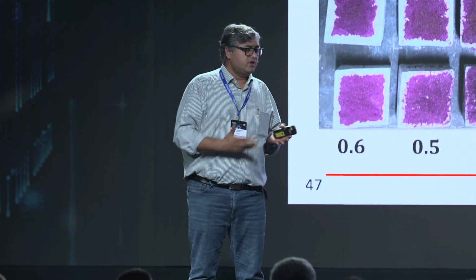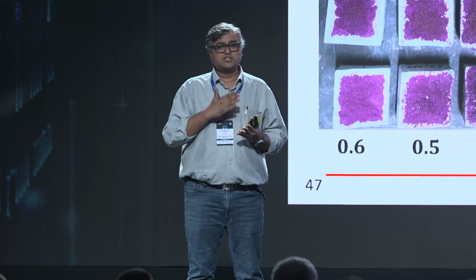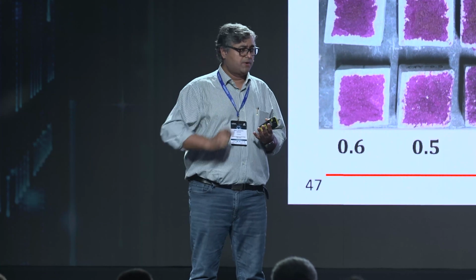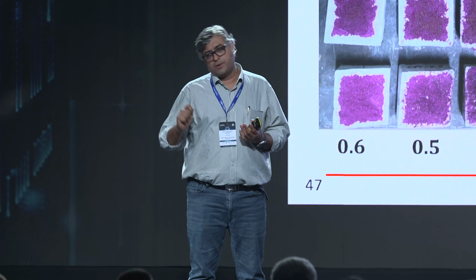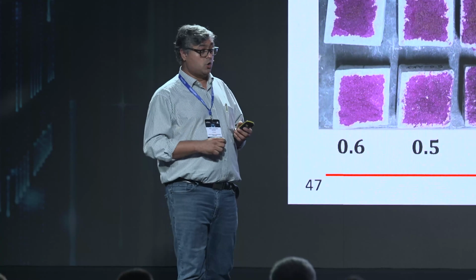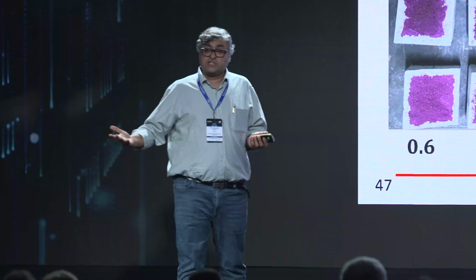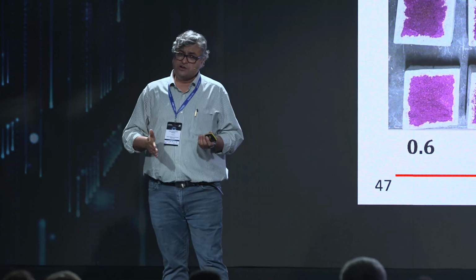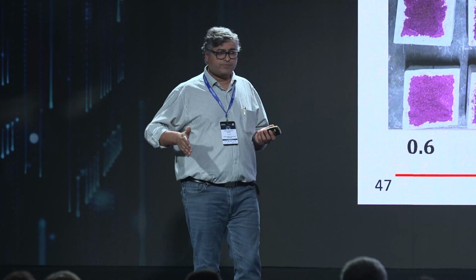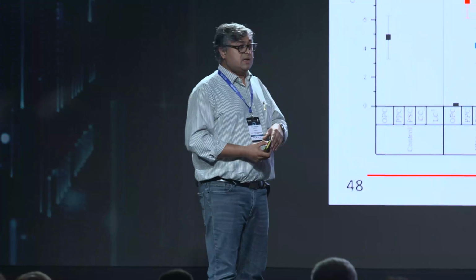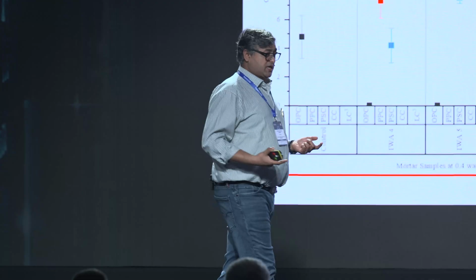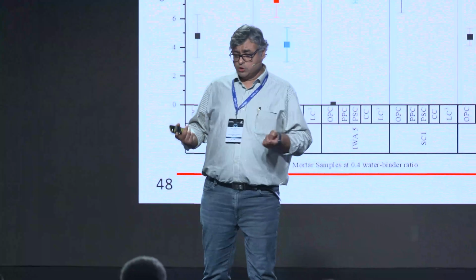Just to be safe, you just make sure that quality control is good on the site. You cannot compromise on clear cover. You cannot compromise on the water to binder ratio when you go down to low clinker cements. And that's essentially all that you have to do. Follow the standard requirements and you're safe. That's what we're trying to tell you over there. And well, if you want to be extra safe, we've got some more solutions for you.